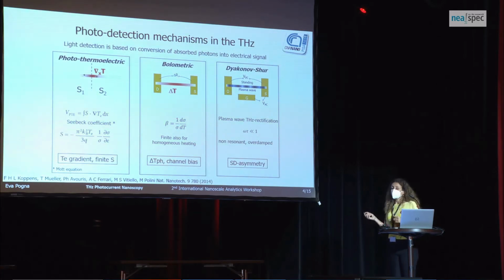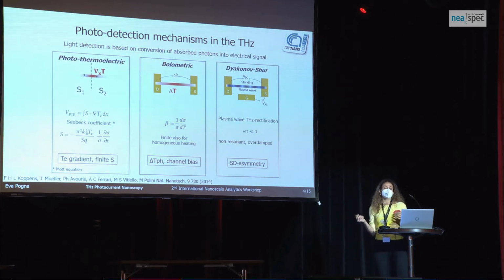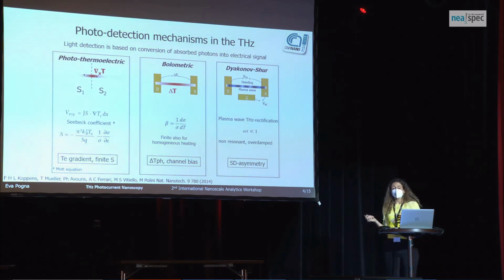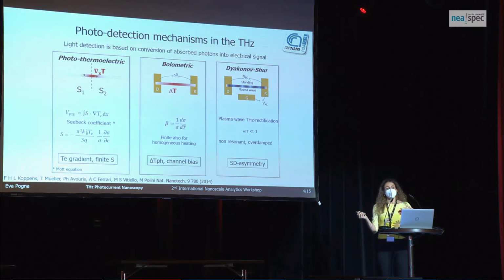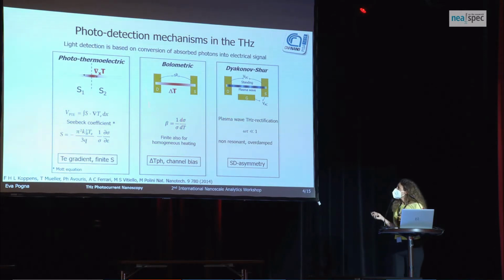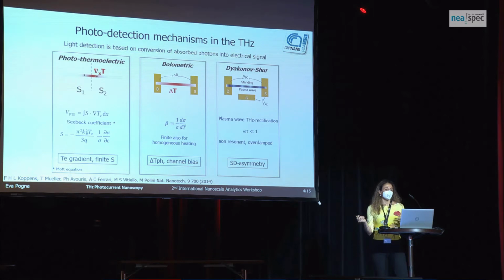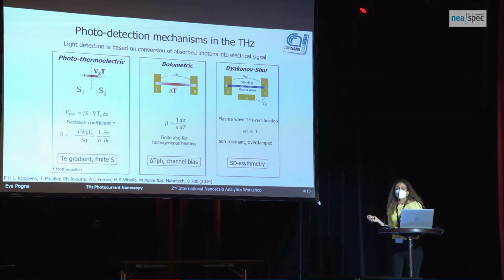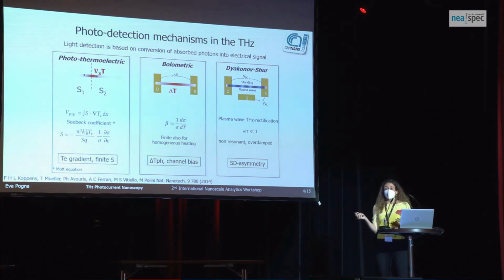But let's have a look at the thermally driven effects. The photothermoelectric effect can arise in a material which has a non-negligible Seebeck coefficient that is spatially varying across the material. This type of material can convert the absorbed light into a photovoltage, which arises every time that we have a gradient in the electronic temperature. Instead, the bolometric effect relies on the heating of the lattice, and it's present every time we have a conductivity which depends on temperature. But in order to measure this effect, we have to apply a bias and monitor the variation of the conductivity.